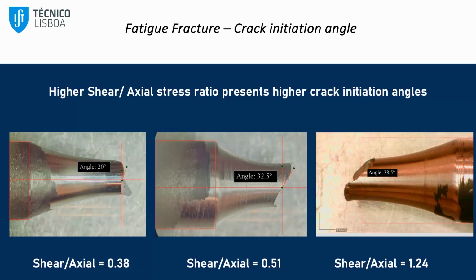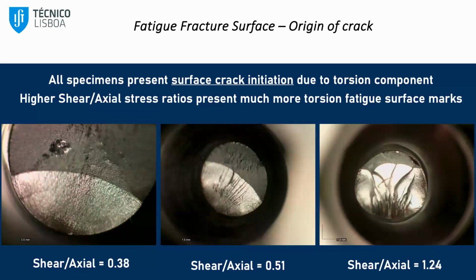So in this case, if you consider the stress ratio, as the stress ratio increases, we can also see that the crack initiation angle also increases. Okay, so it's identified here. We have also looked at the fatigue fracture surface. And if you look here for each stress ratio, you can see the effect of the torsion component. It is more pronounced when the stress ratio increases, as you can see here. So the marks are more predominant in number and shape.